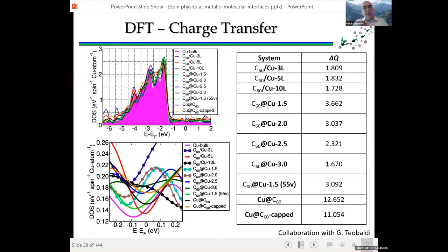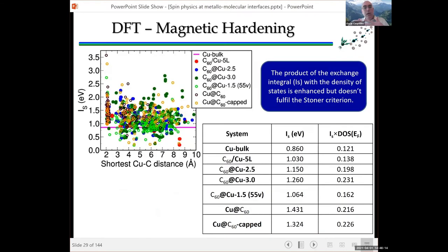Collaborators doing DFT simulations try to explain this. And what they told us is that no matter how you set up the system, you always have a large electron transfer, in particular from copper to C60, of the order of 1 to 3 electrons per cage, and orbital rehybridization of the interface. So the C60 at the interface becomes metallic and forms this electrical dipole with the metal that changes the electronic structure, and that results in a change of the exchange energy. So you harden magnetically your metal. You harden it by about a factor 2 to 3.